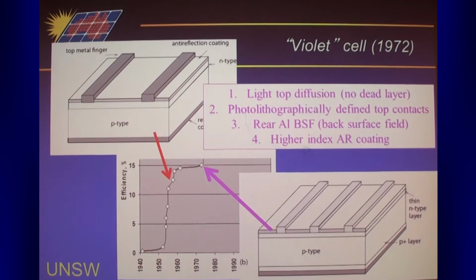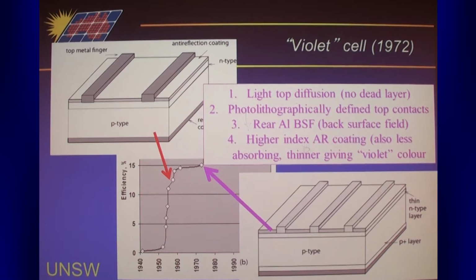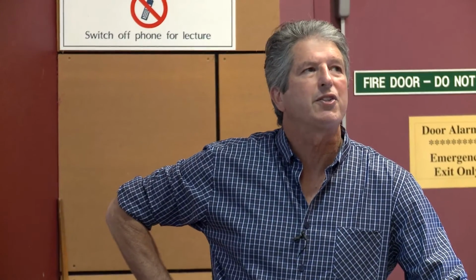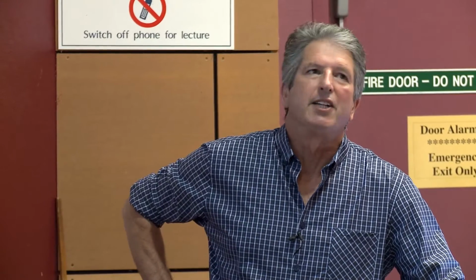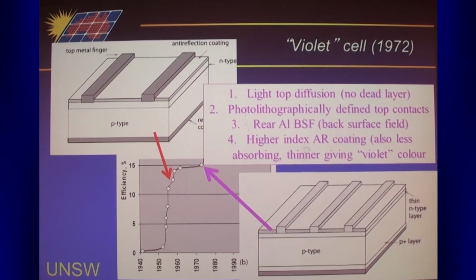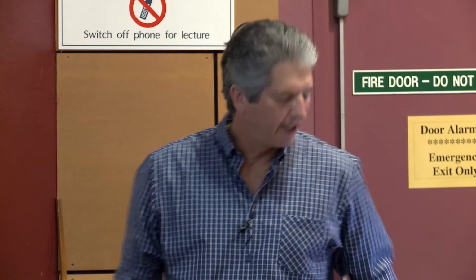Higher index anti-reflection coating, the ones we used before were a little bit low, and as I mentioned last week, it was also less absorbing material. So silicon monoxide used to be used, and titanium dioxide, tantalum pentoxide, and a range of other less absorbing anti-reflection coatings started to be used. And because the cell could now respond better to blue light, because there was no dead layer along the surface, the anti-reflection coating was sensible to make it thinner, because the cell previously couldn't respond to blue light, so you designed the anti-reflection coating for longer wavelengths, but now that you could respond to blue, it was more sensible to have a thinner anti-reflection coating, and the cells sort of look violet, so that's why they're known as the violet cells.